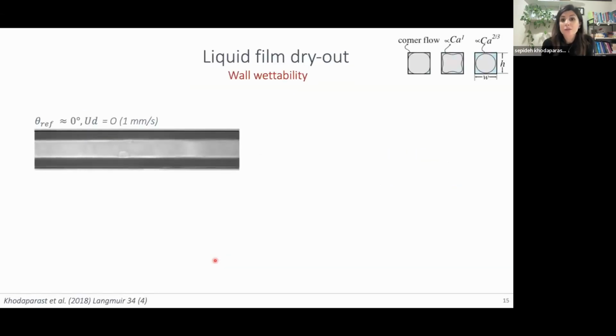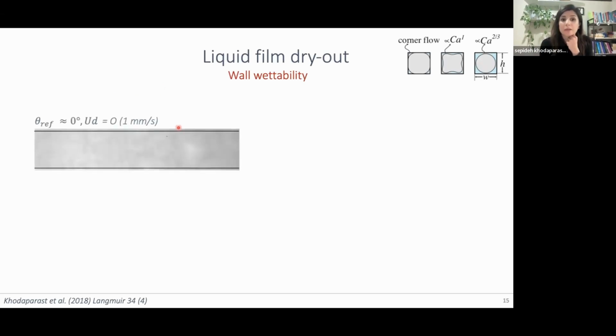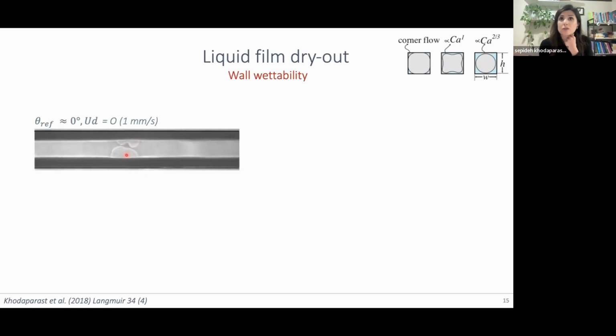So what is the contribution of wall wettability? I promise I'm going to talk about surface interaction. So what's the role of the wall, if you're running the experiments in the same exact conditions, what would happen if you have a more wettable or less wettable wall? In the first video, you're looking at a condition where the wall is quite wettable, but the bubble is moving at quite a low capillary number. So the film is quite thin. And eventually, at some point from the nose of the bubble, you start getting these dry out patches.